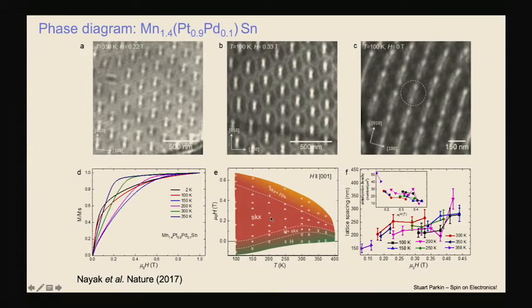And you can see this is the perpendicular field. And at low fields, you actually see a different structure. I'll mention a helical structure. And then you see a wide range of temperature where we see these skyrmions shown here.